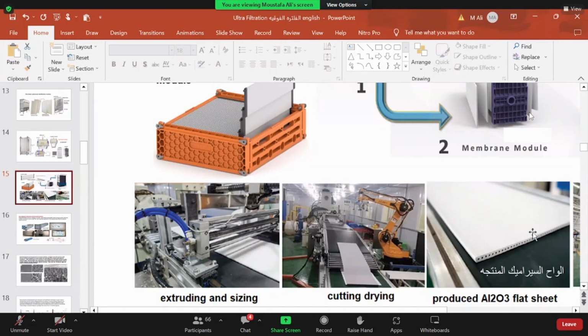So after these 2 layers of coat on the alpha aluminum oxide ceramic membrane surface, it passes through the oven in the same way, as I said, to form this final plate of ceramic membrane. Can we call it spray coating? Yes, of course, it's spray. I just said spray coating. You can say spray coating for alpha aluminum oxide.